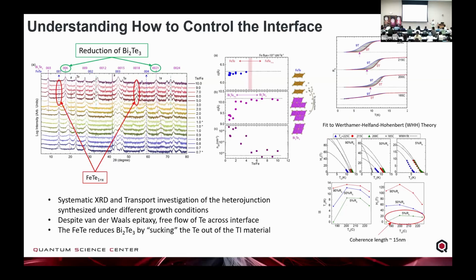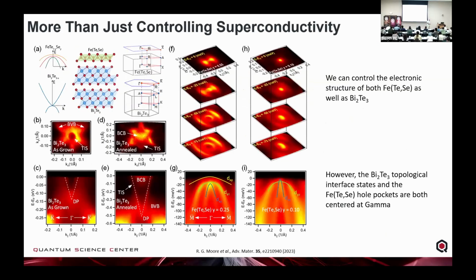And so for the sake of time, I'll skip over this, but we do a lot of X-ray diffraction, a lot of transport properties to confirm that these are indeed superconducting, highly crystalline materials. But here, it's more than just controlling the superconductivity. And so here we're starting to see some of our ARPES data where we can look at the topological insulator underneath, and then we can grow the thicker films and see the superconducting band structure of these materials.